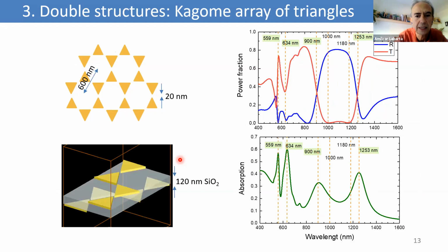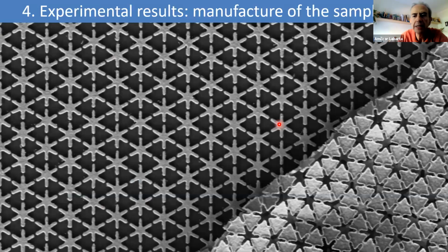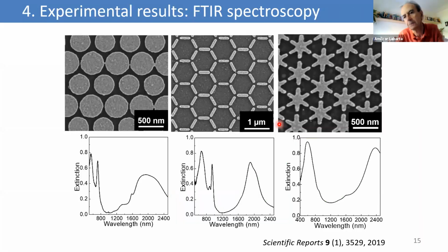We can study, for instance, the intercalation of the two sublattices, and then we can get this kind of phenomenology here. Here we can see a very sharp variation of the transmission in a very small range of wavelengths. This could be also interesting for sensing applications. And finally, let me say that we are, of course, manufacturing these samples. These samples can be manufactured by electron beam lithography. Javier will explain this fabrication in more detail. And these are examples of experimental measurements on these systems, showing these narrow peaks also corresponding to collective excitation.